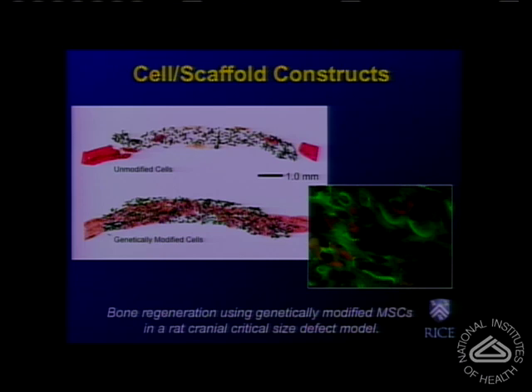And for this reason, we and others have also investigated the transplantation of genetically engineered cells as a means of delivering bioactive molecules locally at the defect site. So rather than delivering bioactive molecules, we transplant cells that overexpress a particular growth factor, and these particular cells are the manufacturing units that produce this growth factor locally. So here we have an example of such a study that involved the genetic engineering of mesenchymal stem cells to overexpress BMP2, and what we find in a critical size defect in the cranium of a rat, when we transplant those cells, is bone formation and union across the defect.